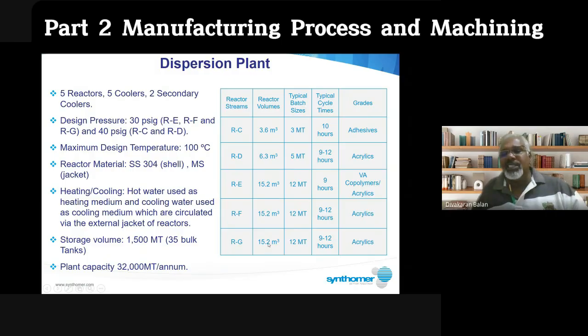And reactor F, reactor G. Reactors E, F, and G are similar in size. Typically the product we produce is about 12 metric tons, and the cycle time for each batch is 9 to 12 hours. In fact, we go up to 15 hours also. This is the maximum design temperature of the reactor. Normally for polymer dispersion, the highest temperature during process will be around 90 degrees C. We are not talking about initial or ending, because initially it will be lower temperature since it's just water, and the ending will be cooled down. So the process temperature, the highest is 90 degrees, and the lowest will be around 70 plus. This is the range of the temperature.